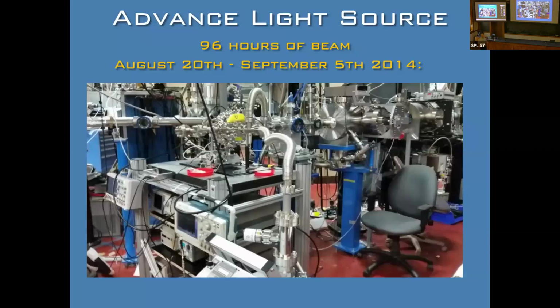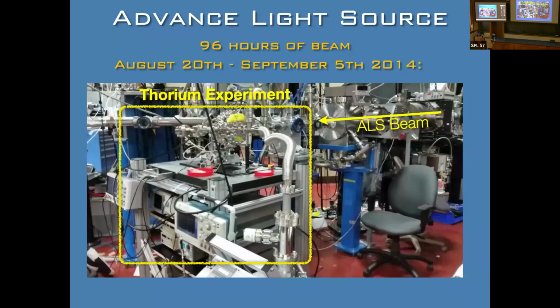And we were already up at the Advanced Light Source. It's a synchrotron in Berkeley. The beam comes in here. This was tunable over 140 to 180 nanometers. This is our thorium experiment on this little cart. It's a super simple experiment. There's just a crystal in the middle. The beam comes in. There's some PMTs here. There's some shutters. Then you illuminate for about half an hour because it's a very long lifetime. You close the beam shutter, open this up, and just see if the crystal glows.